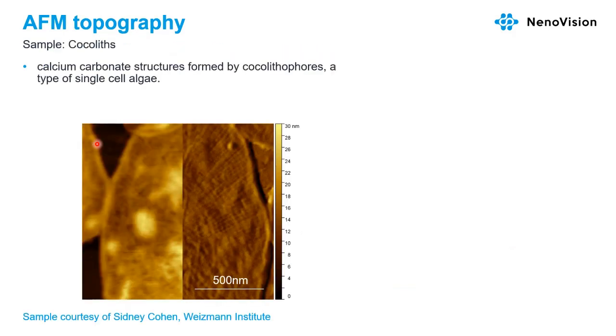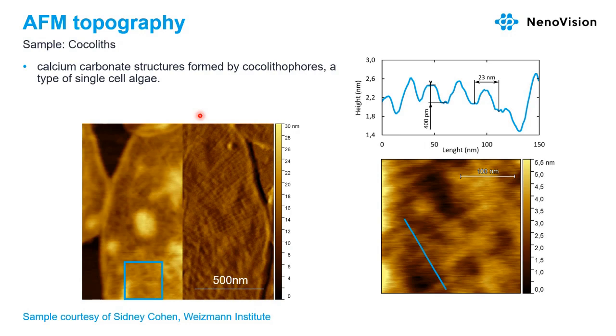Another example is a sample of coccoliths. They are calcium carbonate structures with very tiny features on their surface. We see the AFM topography image and the error, and we see in the detail and in the height profile that we are able to recognize 20 nanometer structures in lateral dimensions and nanometer structures in the Z-axis.